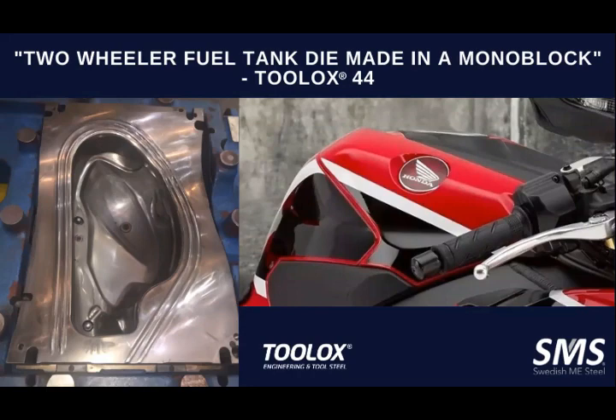No distortion, nothing. We have done nitriding at 550 degrees centigrade. No problem with the distortion. We were able to match it and put it into use. So Toolox 44 plus nitriding, last we have heard that it has run around 5 to 6 lakh shots without any recoating required.